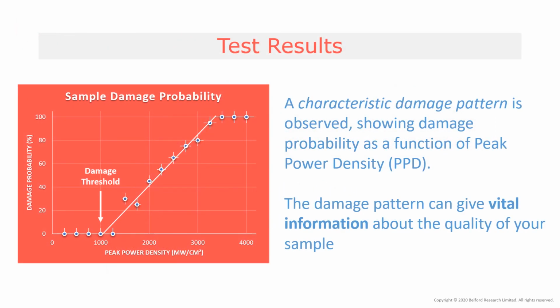Here is the damage profile. We give in-depth detail with each certification. In this case, a graphical determination was possible, and graphical results are far more informative than least fluence. Least fluence is the highest tested value which did not damage. But a graphical result will give far more diagnostic information. The damage pattern, slope, and pre-slope events give vital information about your coating quality. You can see here clearly marked the damage threshold, which is the highest power density that your sample can handle without damaging.